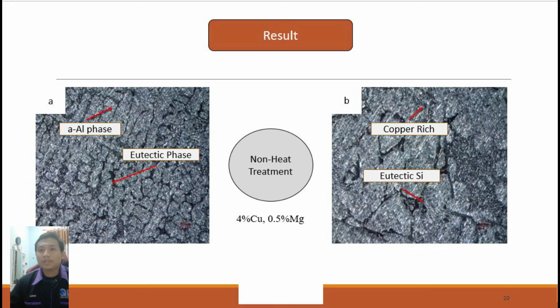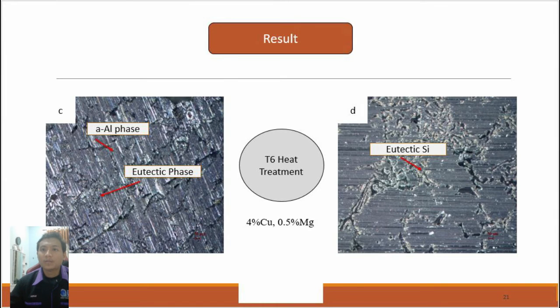We can see in picture B the flakes of silicon in the as-cast modified alloy. The primary alpha aluminum dendrite was composed of eutectic silicon particles, which were present because of the high cooling rate and the low pouring temperature. In picture C, we can see that the T6 heat treatment transformed flaky or lamellar silicon particles into spherical-shaped angular morphology. In the solution heat-treated sample, eutectic silicon particles have been fragmented and spheroidized, while silicon particles have been refined and the edges have a sharper angle than the cast alloy before heat treatment.